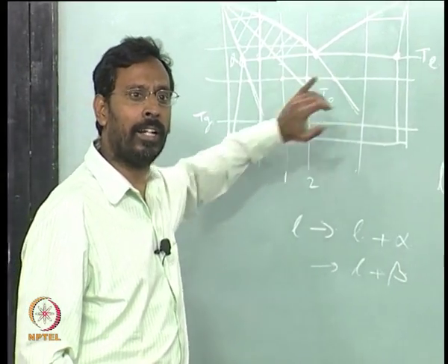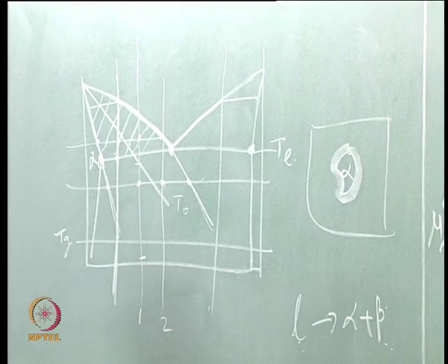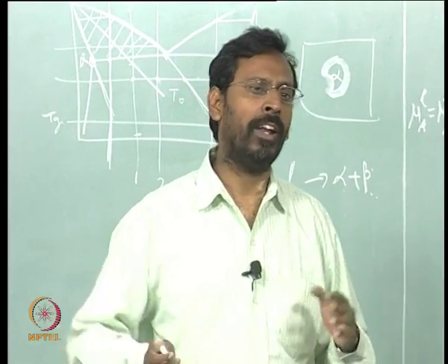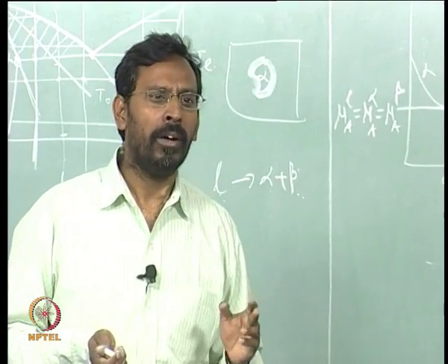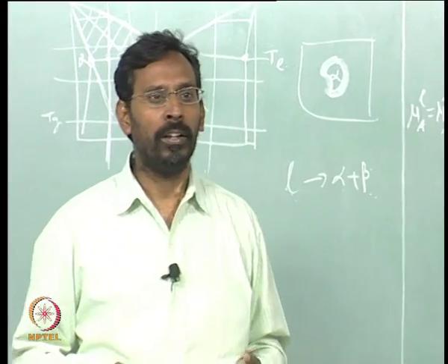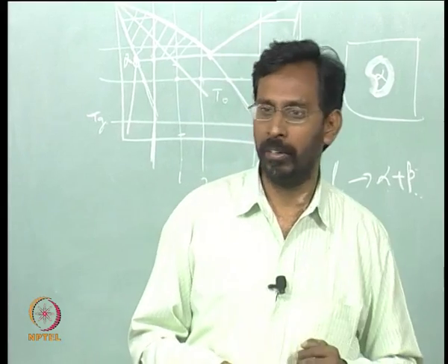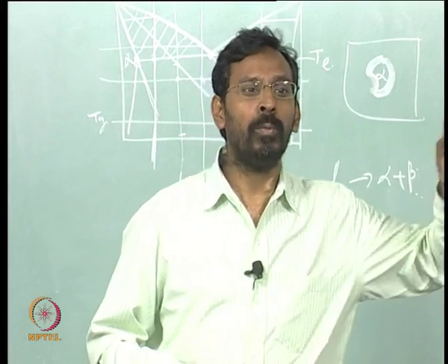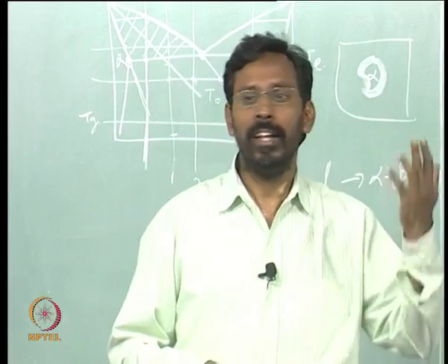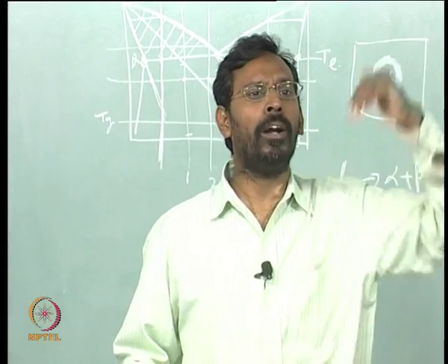And if you think that the temperature is very small, like absolute zero or close to room temperature, whenever we talk of temperature we should remember what we are talking about. For example, many of you know that deformation at room temperature for lead we call high temperature deformation, hot deformation. So with respect to what are we talking? With respect to the melting point of that metal,